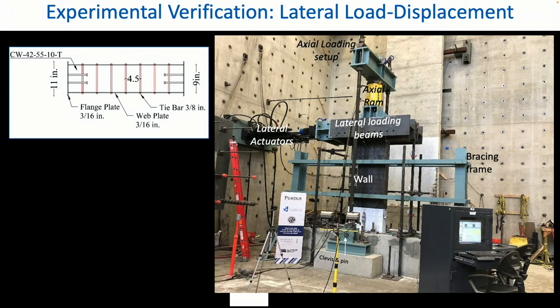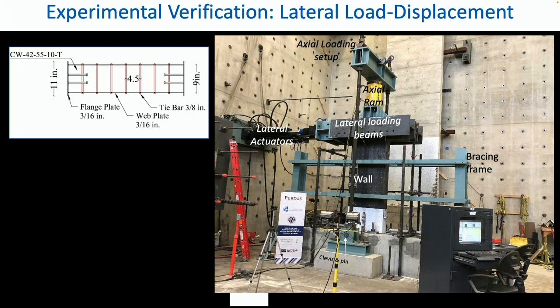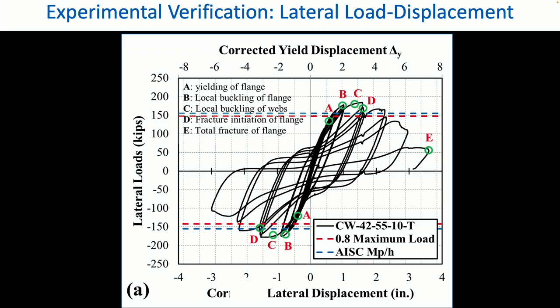So having looked at these recommendations for stiffness and strength, we all want to know whether this is really based on test data and validation or not. The experimental data plays an important role, of course, in all of this research. So we developed some specimens that were about one-third scale representations of the full-scale steel plate composite walls, and we tested them in our laboratory under axial compression and cyclic lateral loading using actuators. You're also noticing the fixed condition at the base of the wall, and this is the location where plastic hinging will form. In summary, this is the lateral load versus displacement response of the specimen that I just showed you.